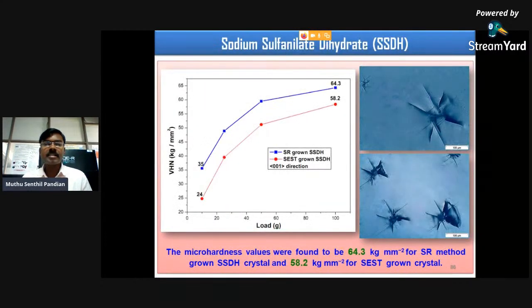To identify the mechanical stability of the grown crystals, Vickers microhardness measurement was performed. This blue color indicates the SR method. This red color indicates the conventional method. Because of the higher crystalline perfection, there is higher mechanical stability and better physical properties. So naturally, the mechanical stability of the SR method grown crystal is high compared to the normal conventional method grown crystal. This is the numerical HV value, in the unit of kilogram per millimeter square. At 100 gram load, it is 64.3 kilogram per millimeter square for SR method. In the case of conventional method, it is 58.2 kilogram per millimeter square. This is under identical condition.